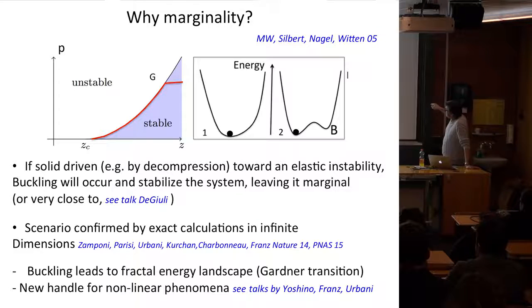So when you reach that point, boom, you have those buckling events, and those buckling events would end up changing the pressure and the coordination in a way that avoids you entering this region, clearly because this is unstable. You cannot stay here. So as you decompress further, you cannot penetrate here, so you're going to actually follow this line, and the dynamics would be a succession of those buckling events. So that was our proposed explanation for why you live very close to this line. How close you live from it will be discussed by Eric, I think, in this conference.